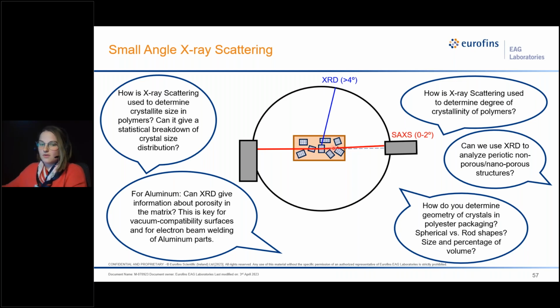But even if you don't have a crystalline material, if you scan the area between 0 and 2 degrees, sometimes out to 4 degrees, but not that much, you're going to get the X-ray scattering. And the scattering can tell you a lot about the makeup of the material, density difference to a matrix, whether you have inclusions or pores, etc. You can learn a lot about polymers and things like that.